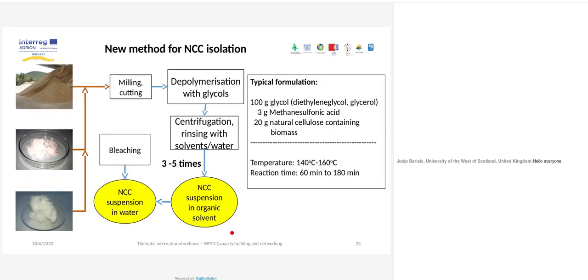Nevertheless, in Slovenia, we've done some work on wood liquefaction and so on, and we found out that it is possible to use this wood liquefaction process also for the production of nanocellulose. How did this happen? Actually, we did this wood liquefaction, and we found that there was some kind of very fine dust clogging our filters. And what was that? Nanocrystalline cellulose. So we modified the process to get a very effective production of nanocrystalline cellulose.